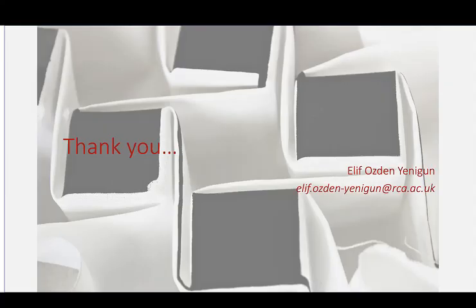So I think that's the critical part that you need to resolve and understand, how your structure behaves. But it's also good, because you understand it's not just about the conductivity range of the material you use, but much more about this cumulative response with the sensing materials. And if you consider along the body, then you also understand that even though you have the same braiding effect, there are different strain ranges. I think data processing and AI are quite critical, because these are the only ways that you can create a very personal data profile. But these are all ongoing studies. But thank you so much for the question.